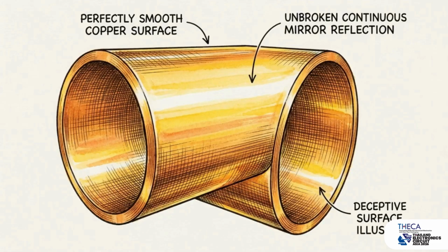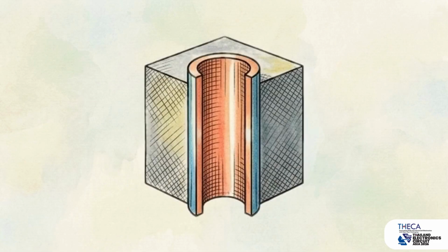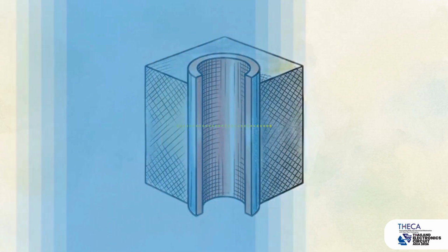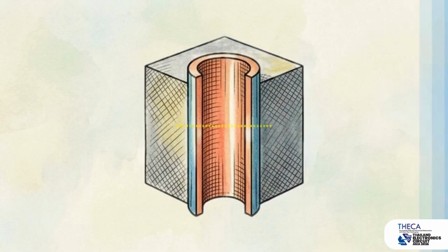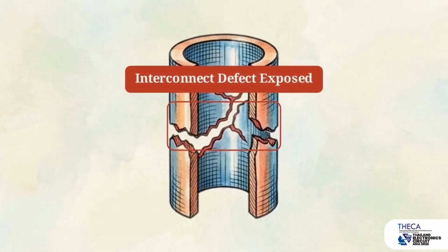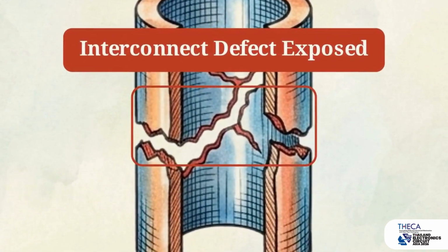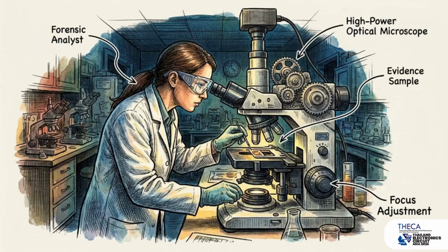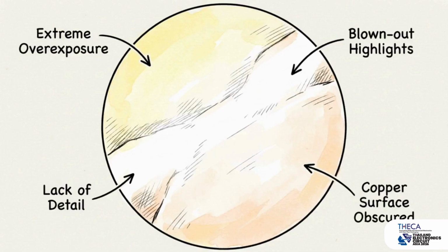Even after a flawless cold cross-section cut, the physical crack is often completely invisible to the analyst. The saw blade's mechanical shearing action drags soft copper across the cut face, physically bridging the microscopic gap. Analysts perform chemical etching with hydrogen peroxide, dissolving this smeared top layer, exposing the dark, jagged void of the separation. The final verification step is optical microscopy. Standard bright field lighting bounces flatly off the copper surface, washing out the delicate details of the crack.